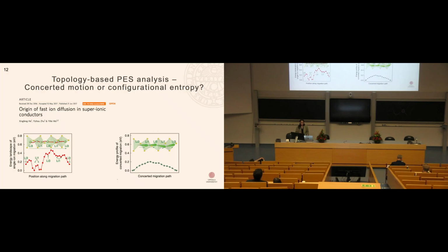But what's particularly interesting is that these results also provided new insights into the diffusion mechanisms. This paper from 2017 was the first to attribute the fast diffusion of this LGPS material, in addition to a few other superionic conductors, to the so-called concerted motion. Concerted motion is when the ions move simultaneously in a kind of liquid-like chain motion. This hypothesis was supported by nudged elastic band calculations. In the first case, they computed the minimum energy pathway for a single lithium ion, which gave one potential energy landscape with quite high energy barriers, and then they did this for several lithium ions simultaneously moving over the barriers, which decreased the energy barriers significantly.